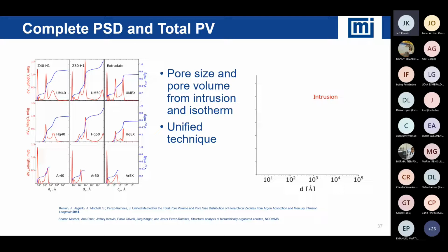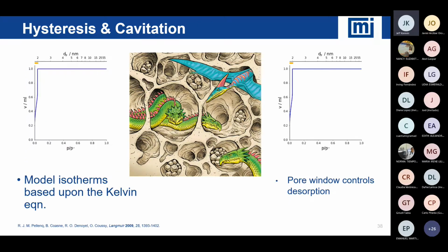When I unify them, when I solve for a single pore size distribution simultaneously using mercury data and gas adsorption data, we see the true trimodal distribution and increased pore volume. So pore volume is more precise if I can unify all of the data. If I treat all of the data as being complementary and not being unique, right? The gas adsorption data complements the mercury porosimetry. We get this very nice result.